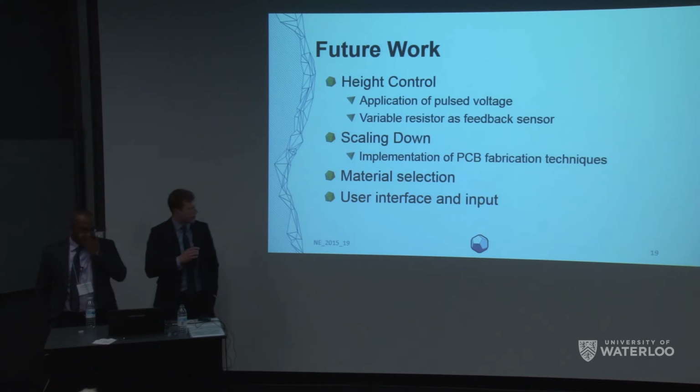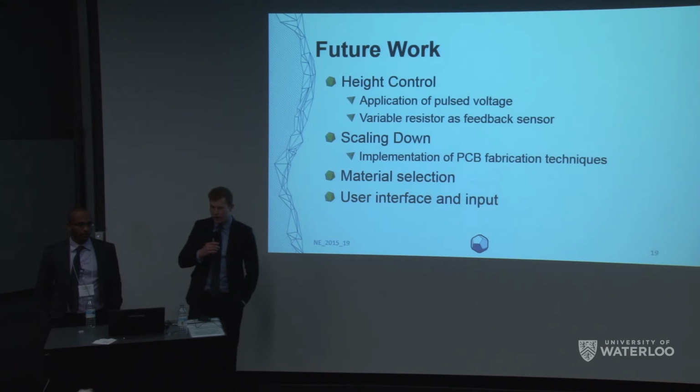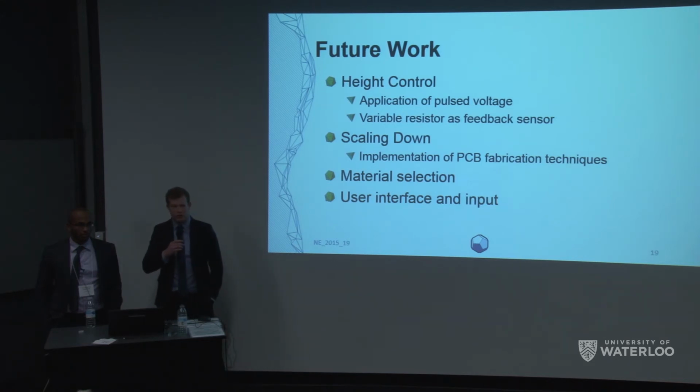And back to materials again. Right now, for our prototype, for the copper contacts, we used C110, a 99% pure copper alloy. That is already showing signs of wear and degradation just from the friction of a very lightweight metal. Metal-on-metal contacts are not known to be incredibly reliable, and they do have inherent friction from surfaces. The topology has a lot of issues, so alloy selection will likely play a huge role. Titanium alloys for the pins probably, maybe some beryllium copper alloys for the contacts. There's a lot of analysis that really has to go into making this a commercially viable product. But given what we've seen here in the analysis, we do think it's possible, with a lot of solid engineering work to be done.